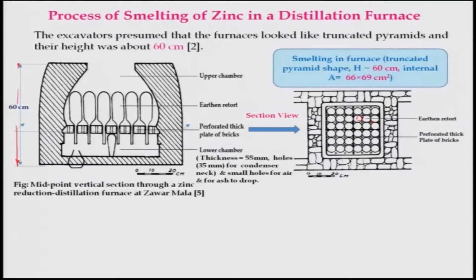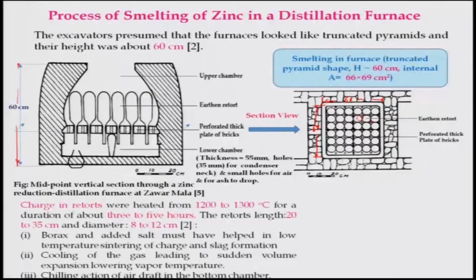And as I told, this furnace is having 69 centimeter, and this is your 66 centimeter cross section. And the charge in the retorts was heated, as I told, around 1200 to 1300 degrees Celsius for a duration of about 3 to 5 hours. And the retorts have a length of around 20 to 35 centimeters and a diameter of 8 to 12 centimeters.